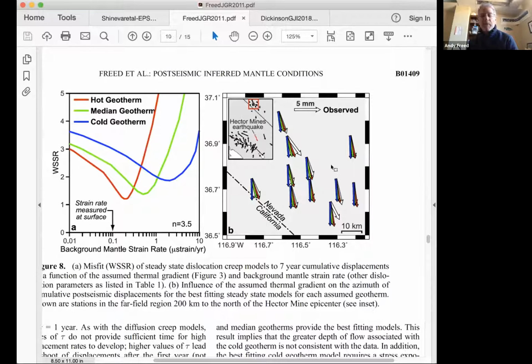displacements. By the way, the reason why it's very different between these two is because the stress dependence of dislocation flow localizes, it makes a very three-dimensional rheology compared to when it's not stress dependent, since you're not working with the stresses themselves so much of the co-seismic. It's a different distribution of viscosity. So this showed we could match time series, we could match far field displacements.